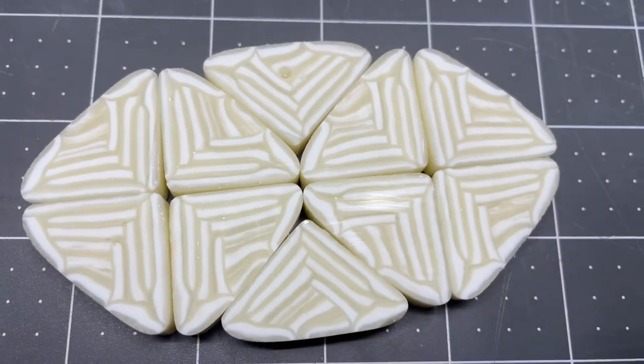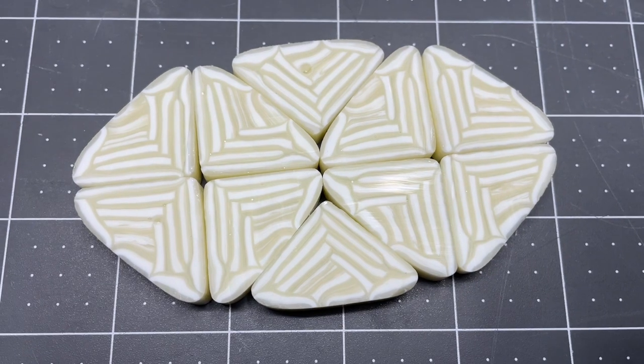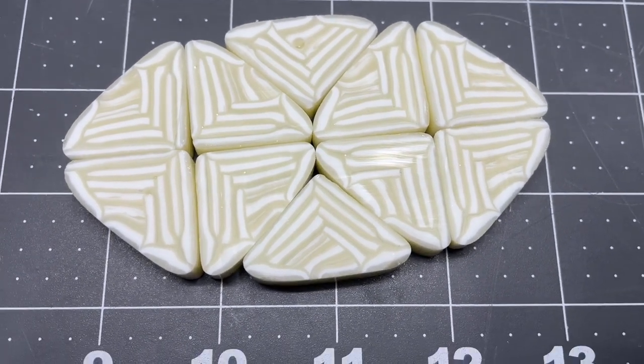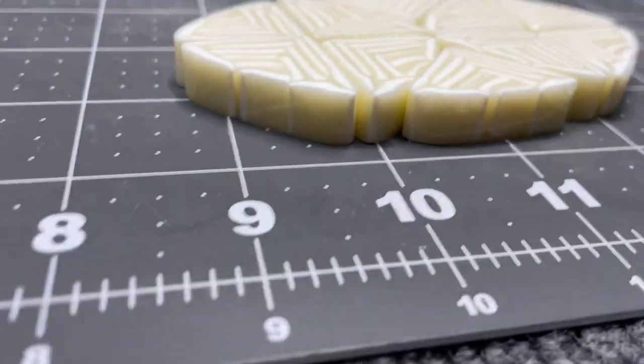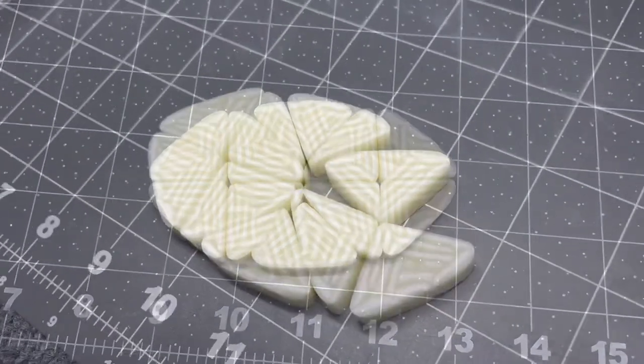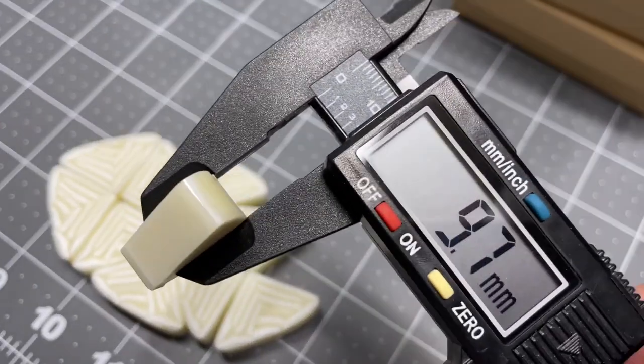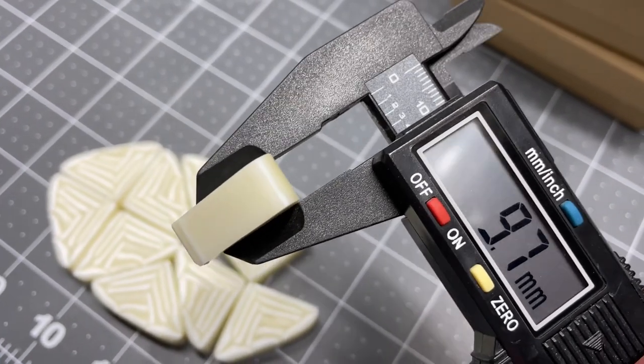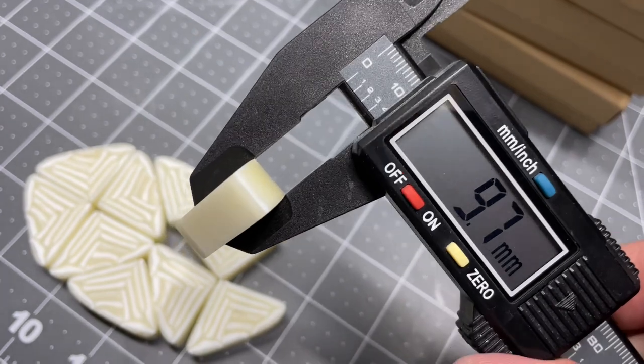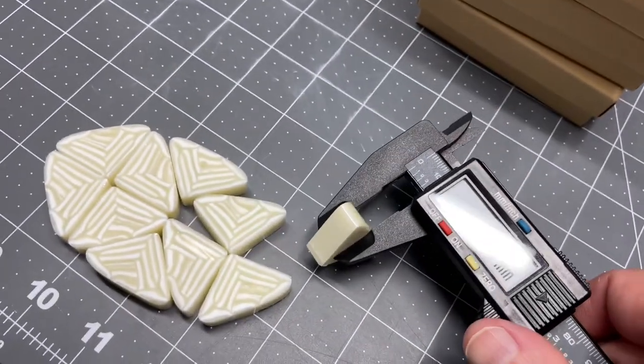You get those really cool colors or reactions with the French vanilla, so that's all that is in there. It's just one color of glass, all from the same sheet, cut up into strips and stacked, fused, cut, super thick. In fact, let me measure how thick this is. As you know, glass likes to be six millimeters. This is 9.7, so this is a full 50%, more than 50% thicker — so this will spread out for sure, but I think it's going to be cool.